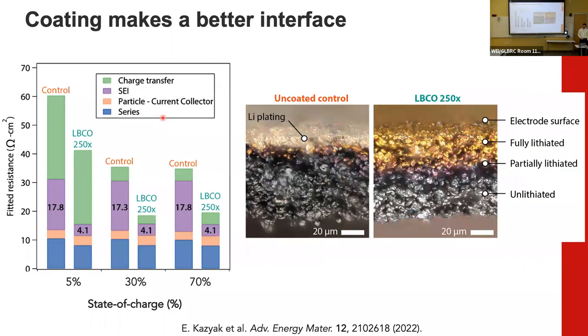But as a result of putting this more ionically conductive coating on these particles, we reduce the resistance that's associated with the SEI, so the purple on this plot. And this is for three different states of charge, 5, 30, and 70%. And in each case, we're reducing it from 17 to 18 ohms centimeter squared down to 4. So like a 75% reduction in the resistance associated with this surface layer.